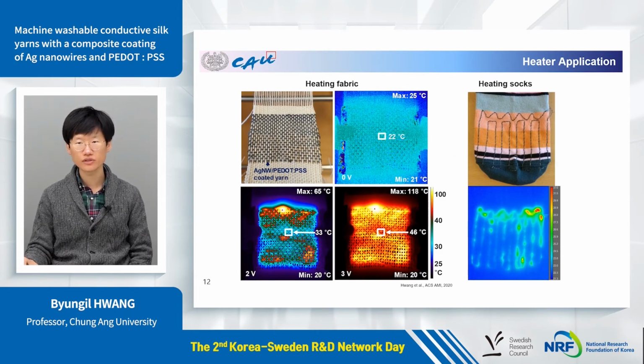Lastly, we demonstrated heating fabric and heating socks using our conductive fibers as a Joule heating element. As you can see in the left image, the heating fabrics achieved high temperature upon a small voltage of about 2 or 3 volts. This clearly showed the potential of our conductive yarns as the Joule heating element of wearable devices.